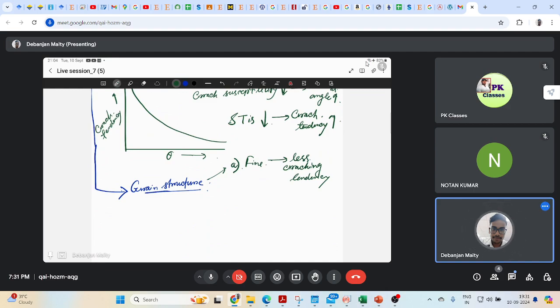So fine equiaxed grains can deform to accommodate contraction strains more easily. During solidification, you will have contraction strain, right? So a fine or refined microstructure can deform to accommodate those kinds of strains more easily. They are more ductile than the columnar grains. I was talking about this also, the in situ healing of cracks. So basically, liquid will be feeding and healing if there is any crack. That can also be more effective in fine grain materials, right?